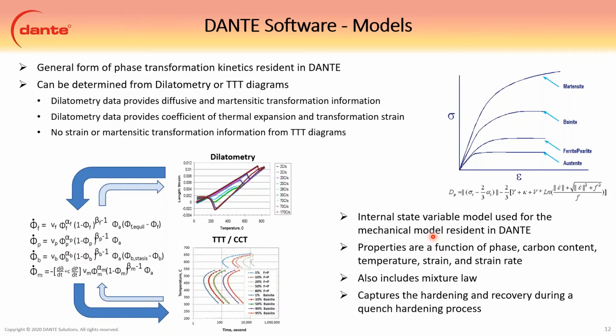The figure on the right, upper right, is representative of our internal state variable model. And we use an internal state variable model instead of the classical stress-strain relationship because it captures the hardening and recovery that happens during the process. And that's not possible with a conventional stress-strain relationship. So the internal state variable model handles all of that. There's like 27 parameters involved in this model, so it is extensive. And the properties are all functions of phase, carbon, temperature, strain, and strain rate. And it also includes a mixture law. So there's a lot going on there. It's a great model. It works really, really well for heat treatment modeling.